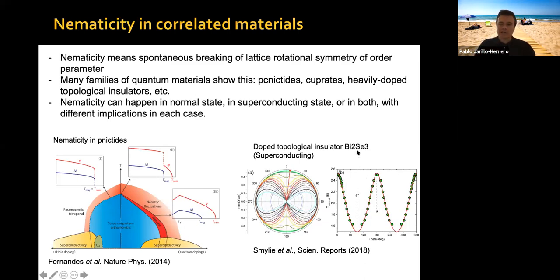So bismuth selenide has threefold symmetry. Okay, so it's a structure, but the TC, rather than having three peaks, has two maxima, okay? Which means it develops twofold symmetry, okay? It goes from C3 or whatever symmetry you have in your crystal lattice to C2 symmetry, you choose a direction, okay? Then this is a signature of this nematicity, okay?